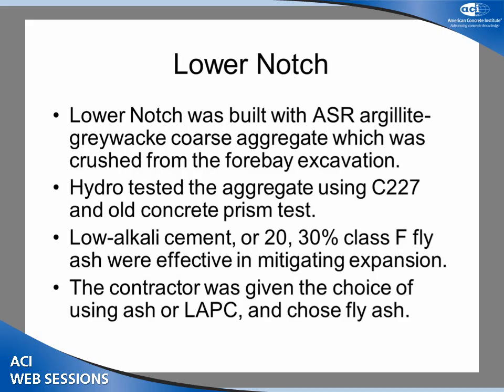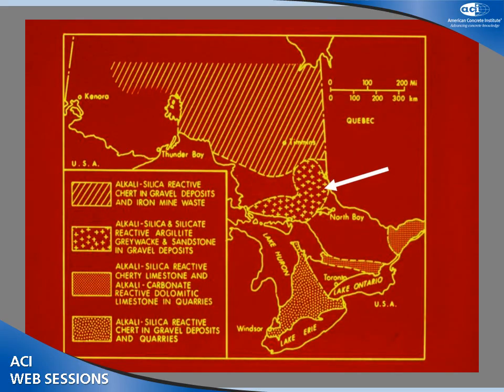They only had the C227 prism test then, and they found with that testing that you could control this with low alkali cement, or you could control it with 20 or 30% Class F ash. And they gave the contractor the choice of which to use. And it turns out the low alkali cement generally was difficult to obtain and more expensive, so they ended up bringing in the fly ash by train loads, and used high alkali cement in that project. There's the arrow showing where it is. It's on a map of Ontario with reactive rock types. So Toronto's down lower. And we're hidden under where it says USA somewhere.